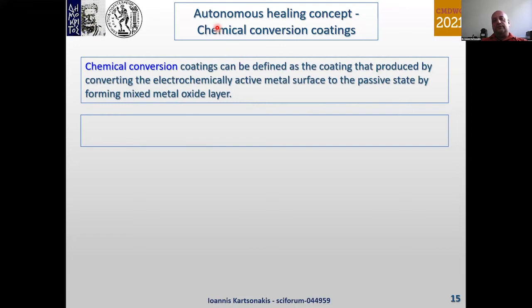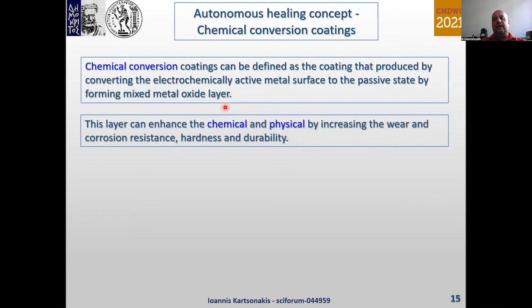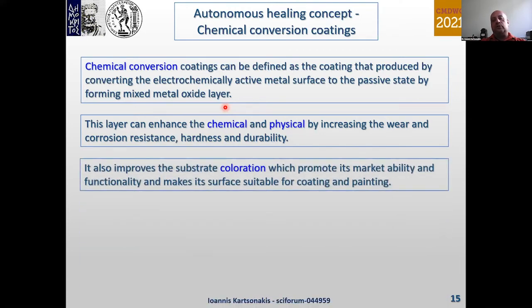For the autonomous self-healing coatings, one category is chemical conversion coatings. These coatings can be defined as the coatings that are produced by converting the electrochemically active metal surface to the passive state by forming a mixed metal oxide layer. This layer can enhance its chemical and physical adsorption by increasing the wear and corrosion resistance, hardening, and durability. Also, it improves the substrate coloration that therefore can promote its marketability and functionality, and therefore the surface can be made suitable for coating and painting.